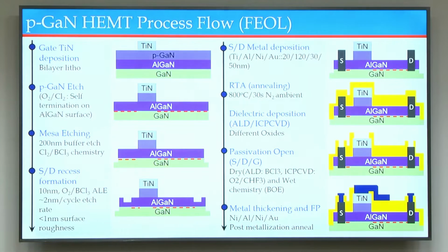Source drain contact. So in this case what we found is that no matter what you do, if you are not doing a recessed source drain contact, you are not going to make good ohmic contacts. You will always have very high resistive contacts, most of the time Schottky contacts. So you have to develop a recess recipe for these contacts, and in this case we are talking about just a few nanometers of recess. So a highly controlled etch, where if you are etching 4 nanometers, you are only etching 4 nanometers throughout the wafer, which is also very difficult.